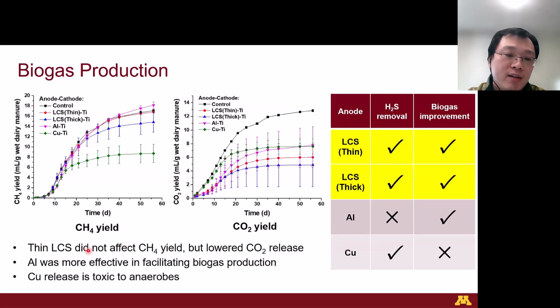Aluminum was effective in facilitating the biogas production by improving the methane yield and also reducing carbon dioxide. But copper was toxic to the anaerobes producing gas, which resulted in a huge decrease in both the methane and the carbon dioxide production. Therefore, we can conclude that low carbon steel anodes could be a viable material for balancing the hydrogen sulfide removal and the biogas production or the biogas quality.